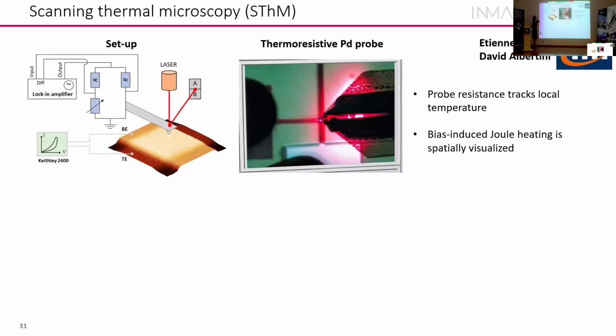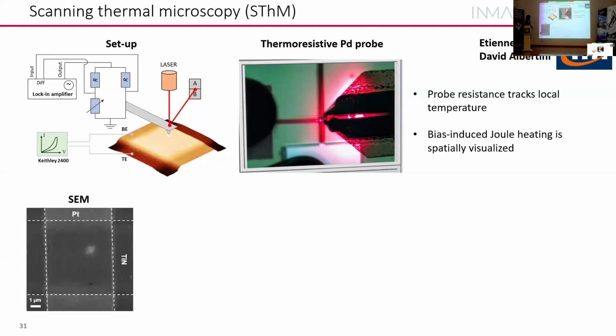So this was done in collaboration with the INL Institute in Lyon, during the last months now, and they use a technique called scanning thermal microscopy. It's like an AFM tip, let's say, but made of palladium, and they measure the electrical resistance, which gives them information about the temperature. So we could apply a voltage and at the same time measure the temperature changes in our sample.